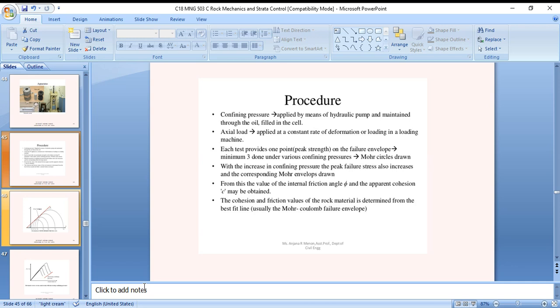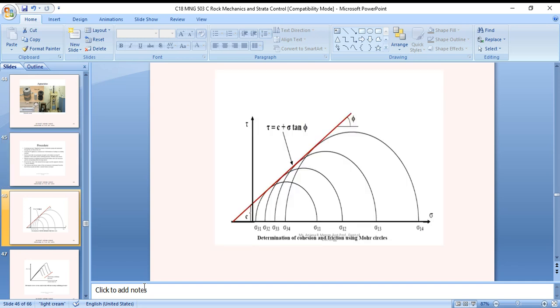Axial load is applied at a constant rate of deformation or loading in the loading machine. Each test provides one point, the peak strength, of the failure envelope. A minimum of three tests under various confining pressures are done, and Mohr circles are drawn. With increasing confining pressure, the peak failure stress increases. The corresponding Mohr envelopes are drawn. From this, the value of the internal friction angle phi and the apparent cohesion C may be obtained. The cohesion and friction values of the rock material are determined from the best fit line, usually the Mohr-Coulomb failure envelope. This is the determination of cohesion and friction using Mohr circles.